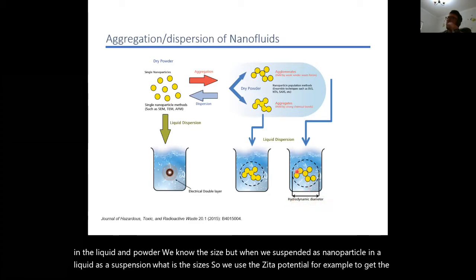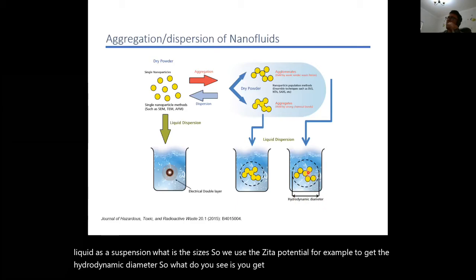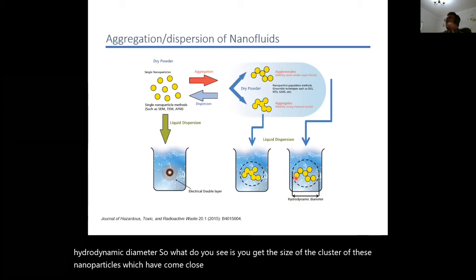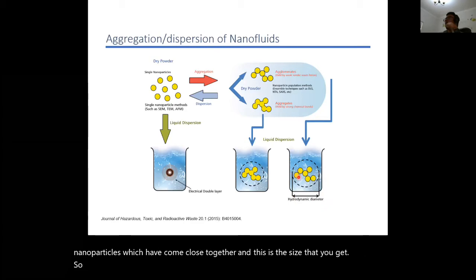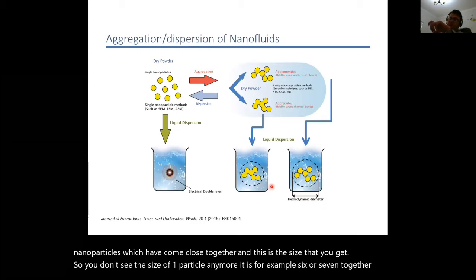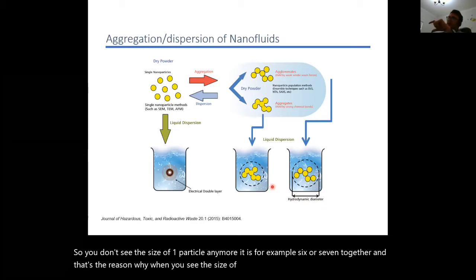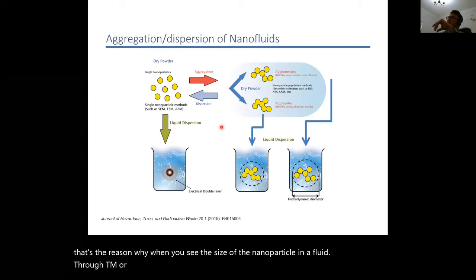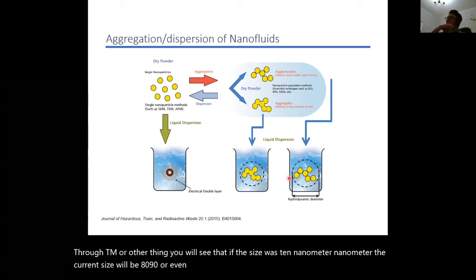So what you see is the size of the cluster of these nanoparticles which have come close together, and this is the size that you get. So you don't see the size of one particle anymore. It is, for example, 6 or 7 together, and that's the reason why when you see the size of the nanoparticle in a fluid through TEM or other methods, if the size was 10 nanometers, the current size will be 80, 90, or even above 100. That is because we still have two challenges of stability.